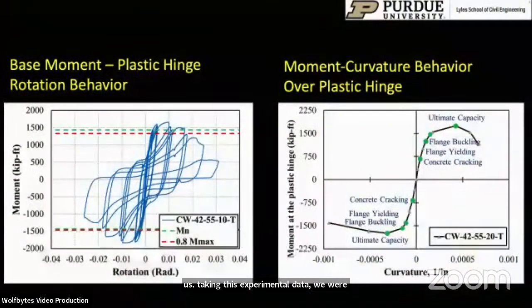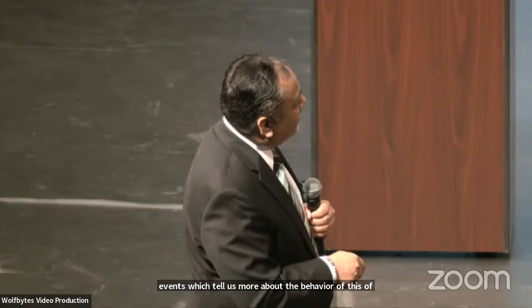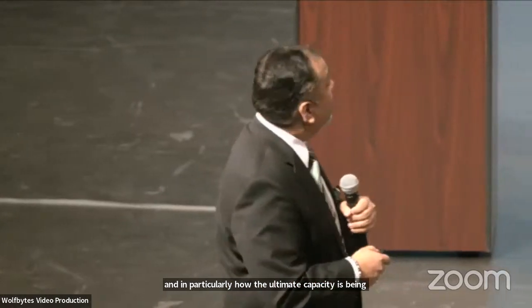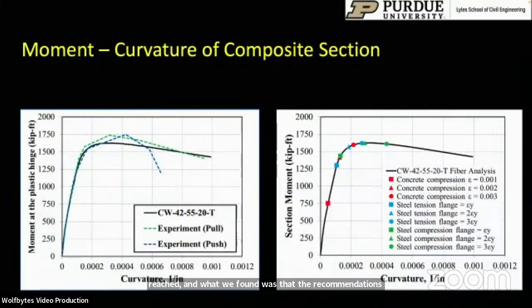Taking this experimental data, we were able to develop the plastic hinge versus rotation response. This is the moment versus base rotation, or the plastic hinge rotation response. And the backbone of that is shown right here, along with the occurrence of various events which tell us more about the behavior of this specimen, and in particular how the ultimate capacity is being reached. And what we found was that the recommendations for stiffness and strength compared very well with the experimental data.